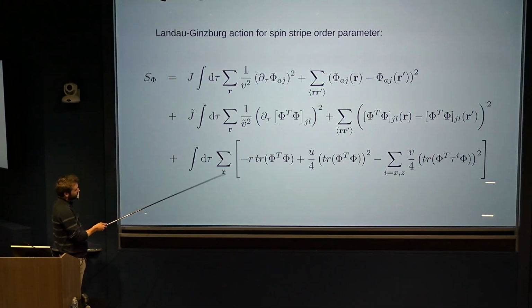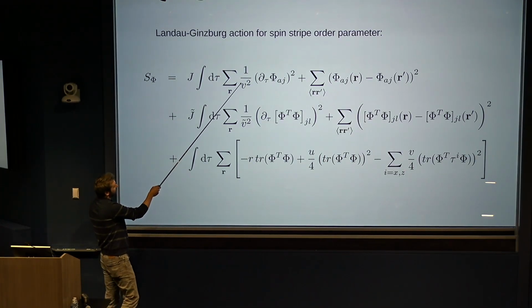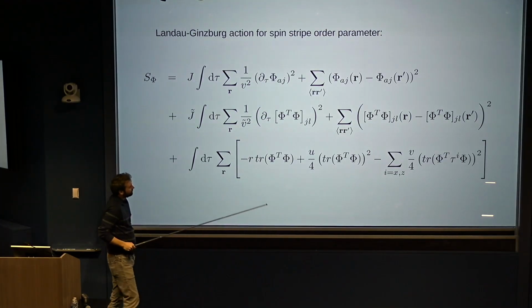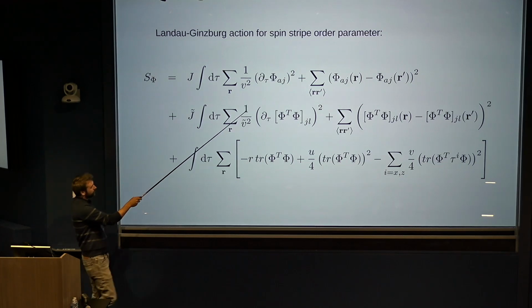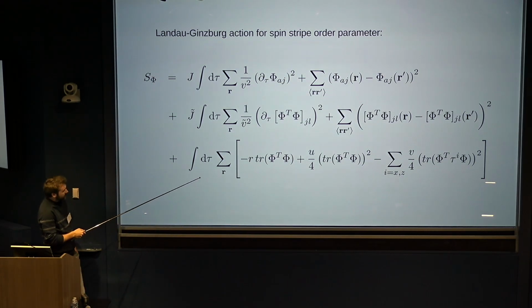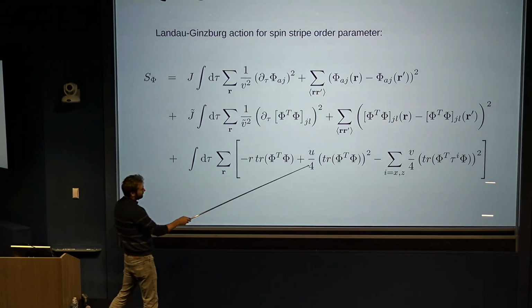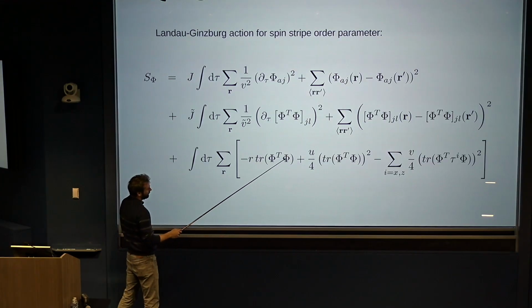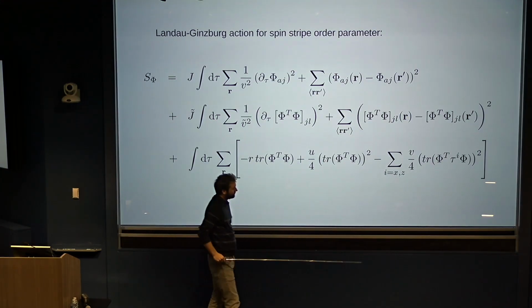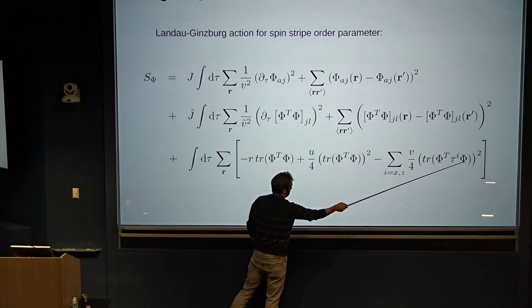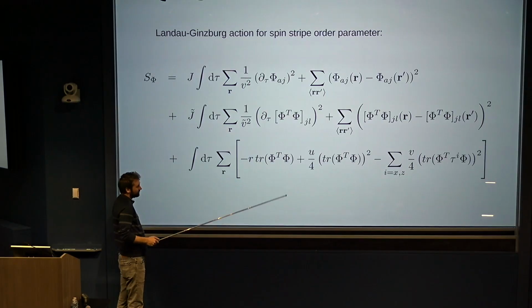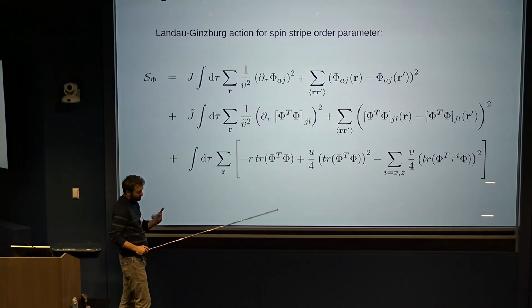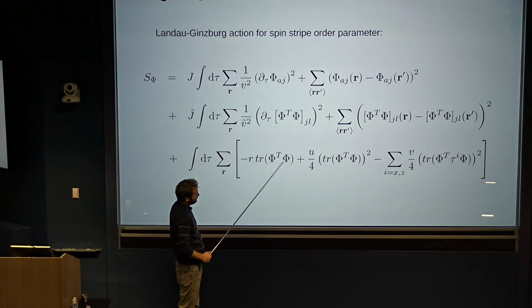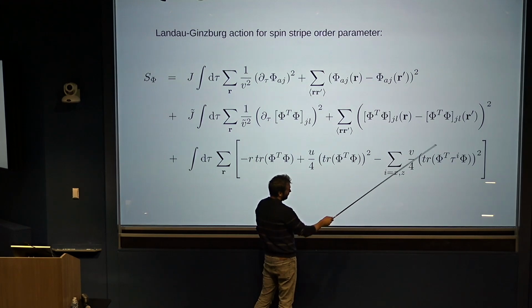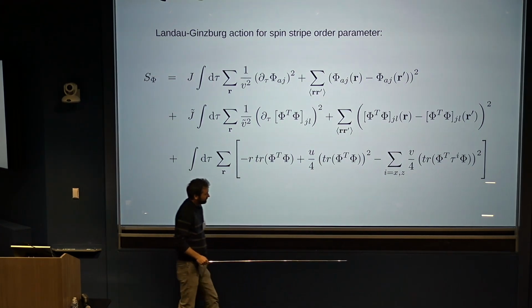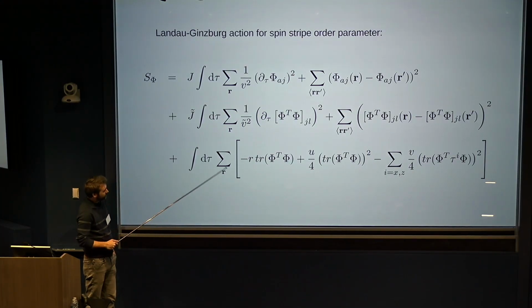It has a lot of terms, but actually you know most of them. The first terms here are standard temporal and spatial stiffness terms for the order parameter field phi. The terms on the last line, the first two are just the standard Mexican hat potential terms. And then this other quartic term is a term which ensures that phi indeed describes spin density wave order. Because this field could also describe, for example, spin spiral order that would have the same type of order parameter fields. But this quartic term here ensures that phi indeed realizes a spin density wave state. Okay, so this last line is just a field potential term.